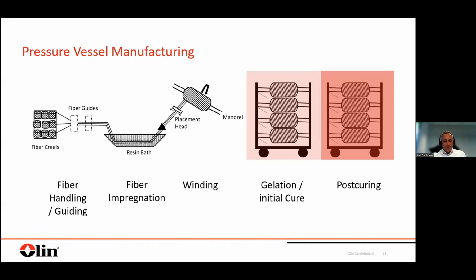If we look at this process, basically we are starting the process with a creel with the dry fibers on either bobbins or rolls. We have some fiber guiding, and then finally the first point where the resin comes into the game is the fiber impregnation, which, for example, can take place in a resin bath, which in the easiest form would be just an open bath, a reservoir filled with liquid resin. Then we are doing some handling of the impregnated rovings. We are winding it, typically around a liner material, either made of metal or of polymers. Today we see polymers dominating the picture, in particular for gas storage.